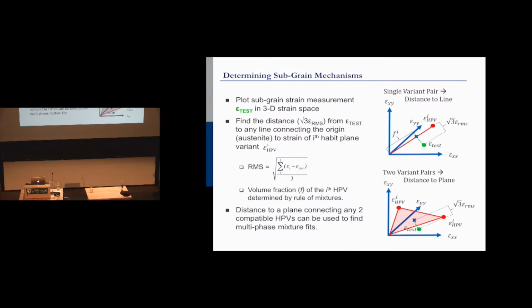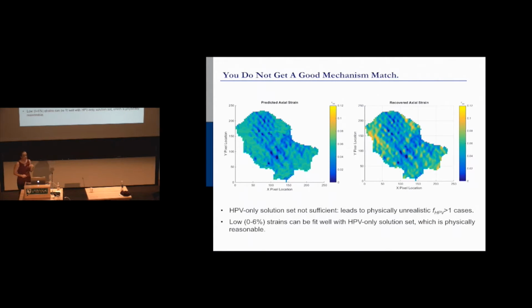You can have 2 variant pairs, which are then going to be distance to a plane. So you can have, you imagine this habit plane variant where you have the layer cake with the austenite. You can actually have 2 different types of those. You can have another habit plane variant that's a different symmetry, again with the austenite. The spatial scale of our data will allow that. And then it would be distance to a plane. So we're able to plot this, and we're able to determine, if we had this mechanism, you plot all the strain data points, you find the mechanism that's active, and then you predict what strain that mechanism would give you.